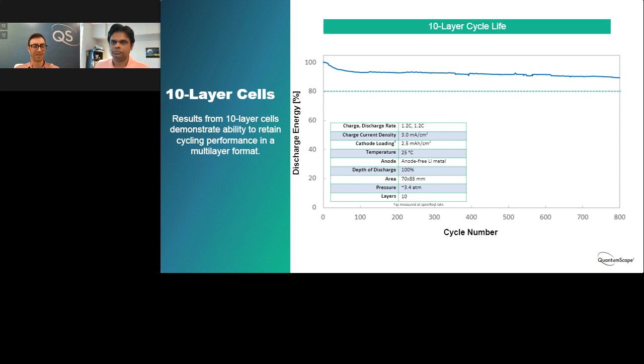density around 3 milliamps per centimeter squared. So the way the math works out here, this cathode loading that I described earlier, of how much capacity you have per area of the cathode, was 2.5 milliamp hours per square centimeter. So when you run that at 3 milliamps, you get 1.2C rates.